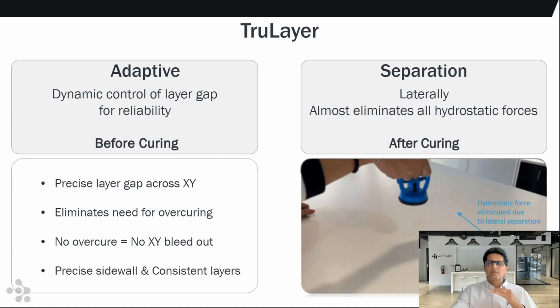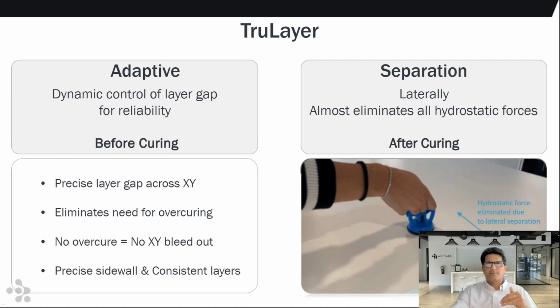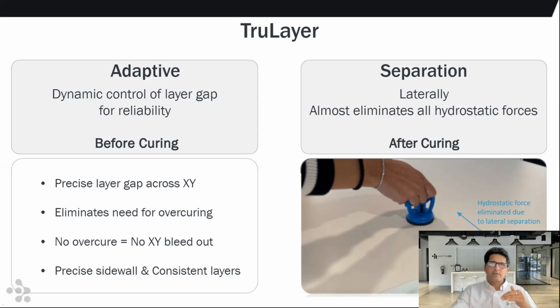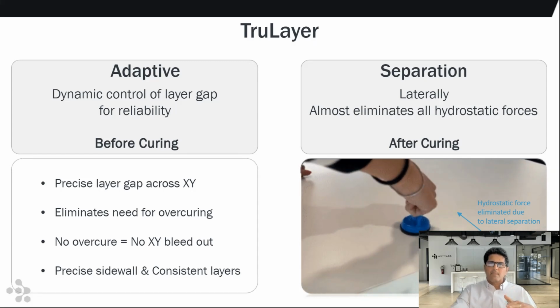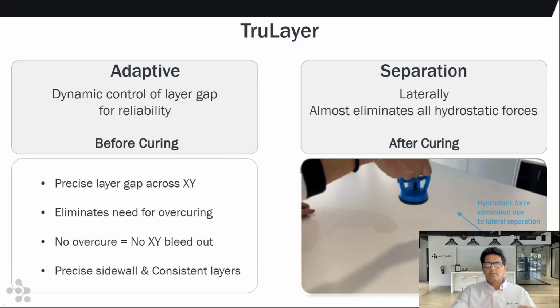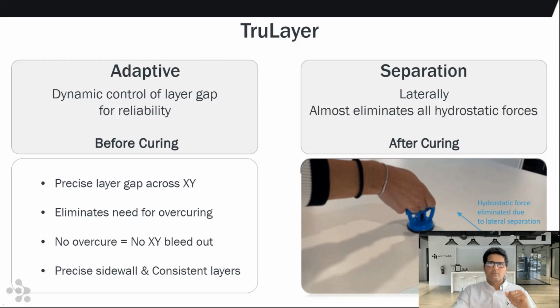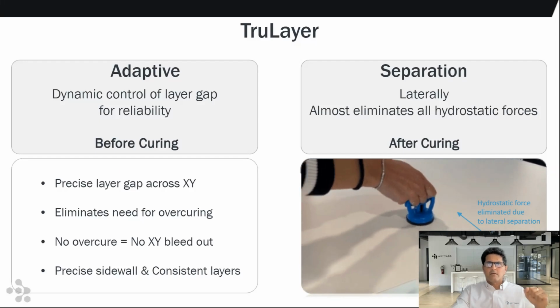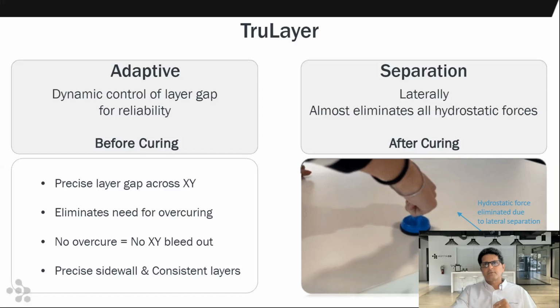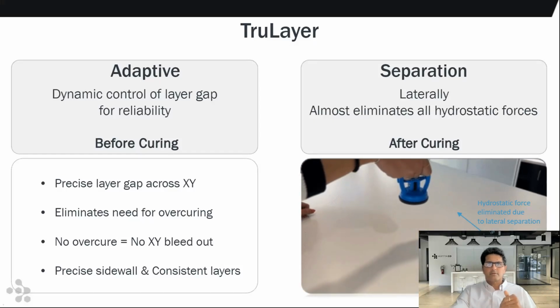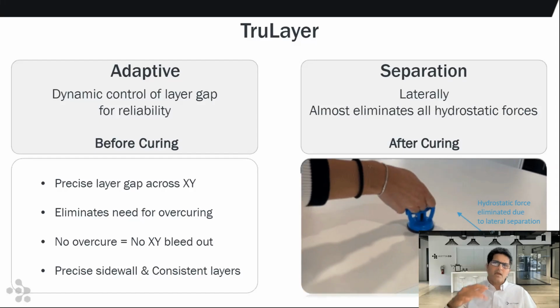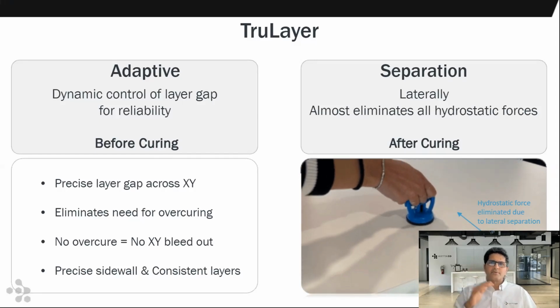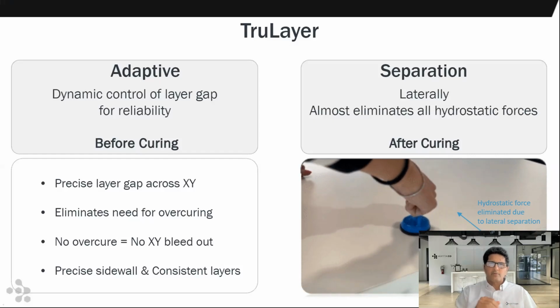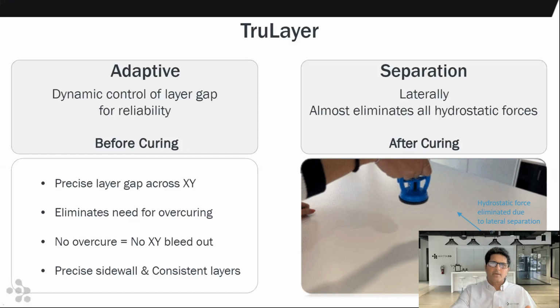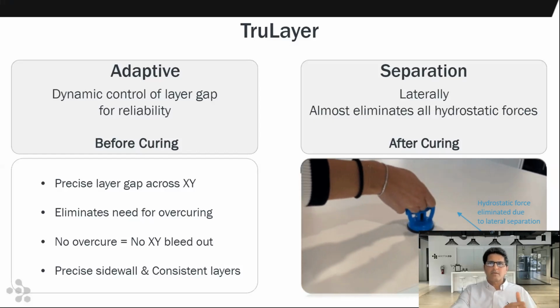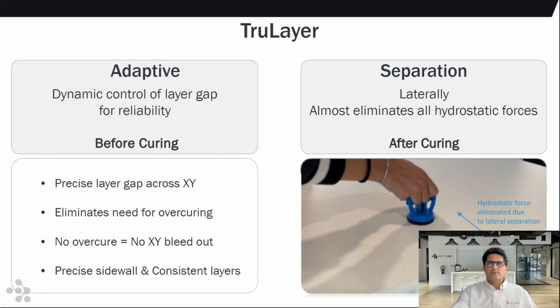It results in absolutely a mirror image of the glass that is underneath it, which is at a 20 micron spec. And you will see that even a 9x6 flat is within 20 microns because we peel the layer in a sideways direction rather than in the vertical direction. We can build about half-meter parts, and through that half-meter dimension, whether it's 25, 50, 100, or 200 micron layers, we get the same exact result all the time.